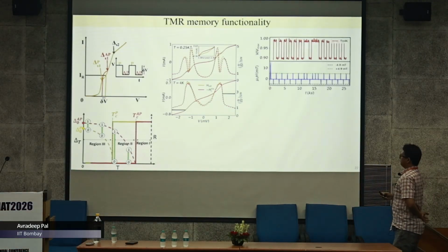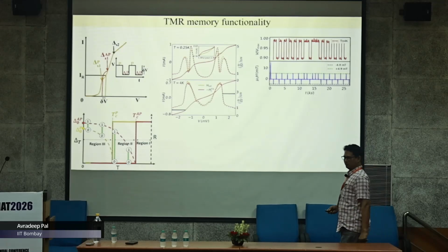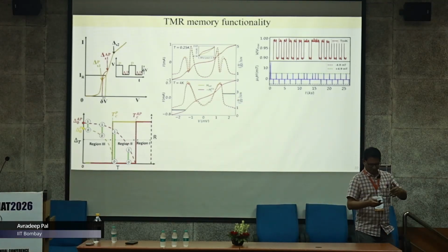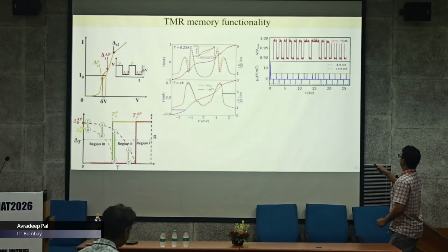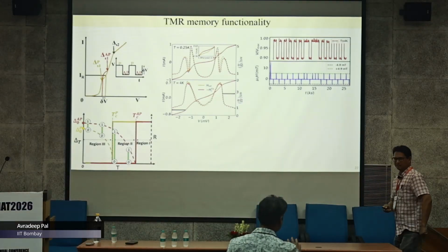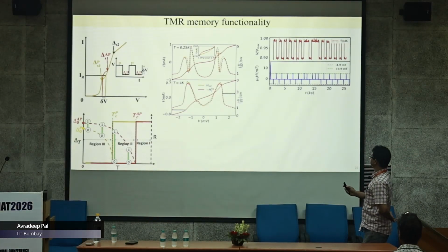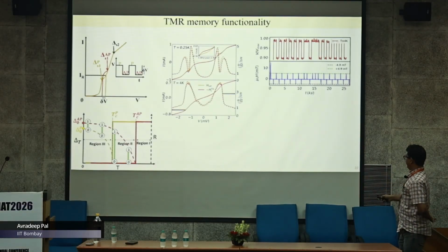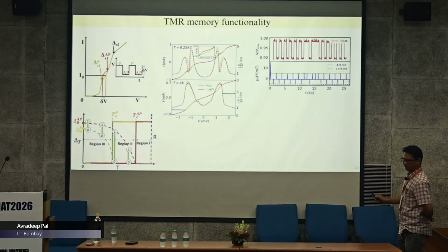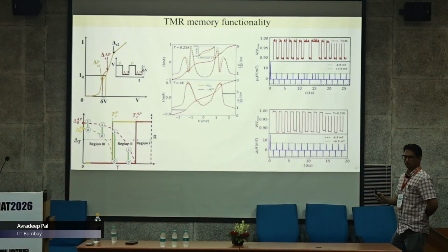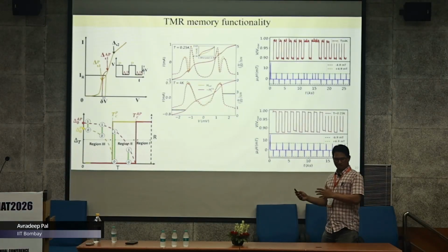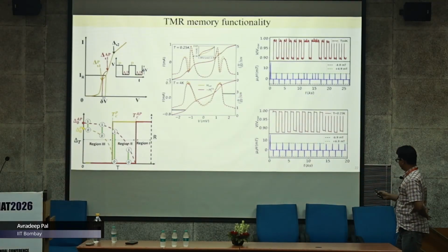Okay, so now we put a read current. Now the experiment is very simple. We put a read current, and we go through the field cycles, and you see there's this nice bistable response. So this is practically my last slide. And as I told you, we can not only get it here, we should also be able to get it at much lower temperatures. So at 0.25 K, thermal effects are gone, and I have this very nice bistable switching in this device.